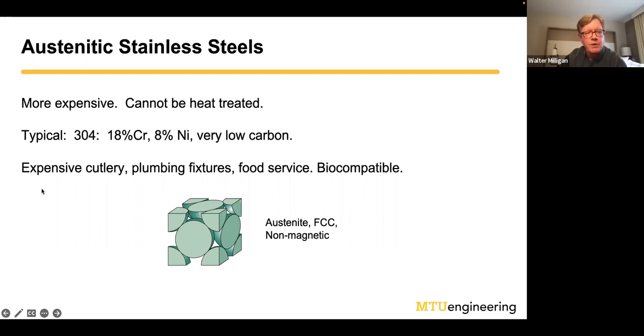So typically we want to have chrome and nickel and very low carbon. And this is useful for expensive cutlery like knives and forks and spoons. It's the most common material for plumbing fixtures. If you go to Burger King or something, you see the shiny stainless steel countertops, they're all made out of this. It's also biocompatible, so there are some implant materials that are made out of this. And once again, this is the face center cubic phase, which is austenite, and it's not magnetic. And so that's the third class of steels.